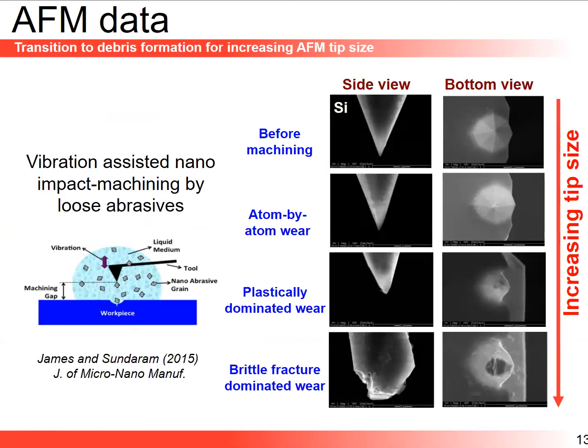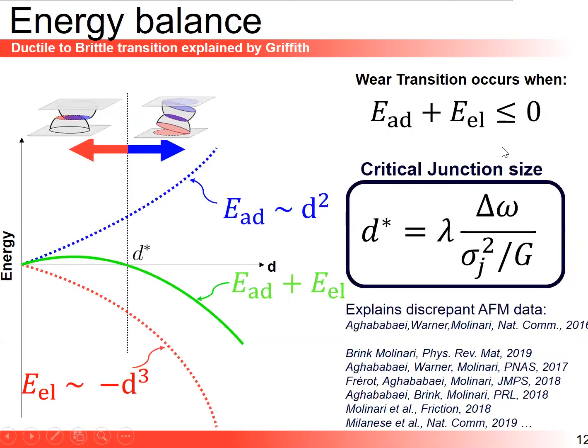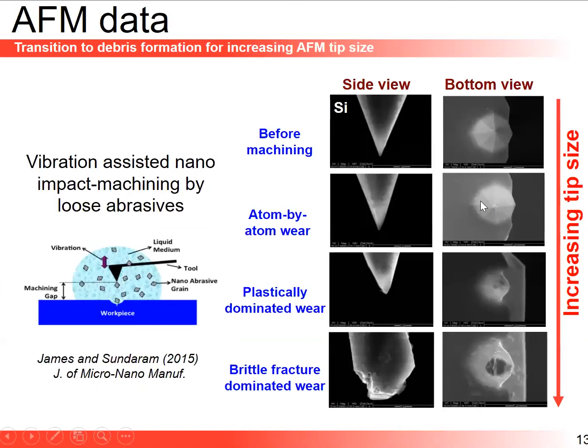Okay, so I will not be discussing much what we did in this paper with regards to comparison with AFM, but this simple equation could explain a lot of discrepant AFM data. I'm just citing here one paper where they increased the tip size of the AFM going up, and they reported that they transitioned from plastically dominated wear for narrow tips to brittle fracture dominated wear for large tips. So precisely what we are saying, and there's a lot more data we could discuss on this.